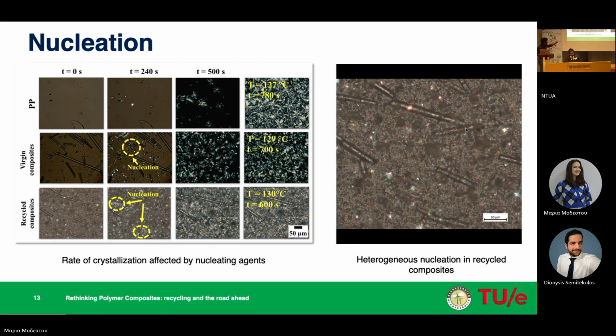So as we can see here, pure polypropylene will crystallize somewhere around 127 degrees Celsius, and in order to fully crystallize, this pure polypropylene would take somewhere around 780 seconds, which is almost over 10 minutes. But in the case of virgin composites, the crystallization time has come down to around 700 seconds, and the crystallization temperature has also increased to 129 degrees Celsius, which obviously shows the effect of virgin fibers inside the polymer matrix, which helps the crystallization process.